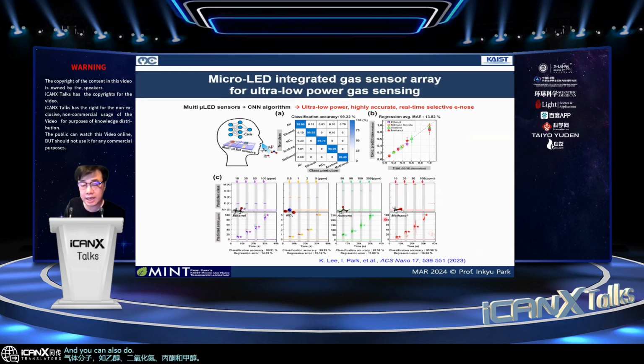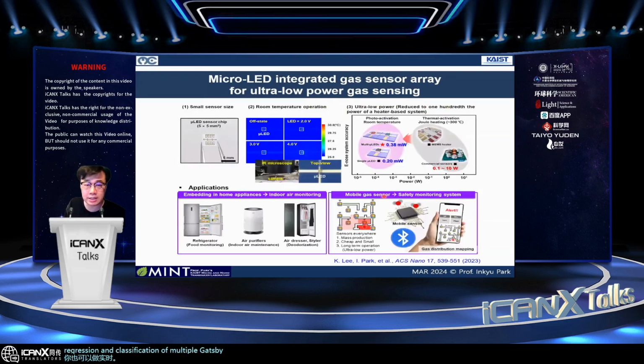And you can also do the real-time regression and classification of multiple gas species. And the biggest advantage of this one is, as I said, the power consumption. As compared to the microheater platform, usually the commercial gas sensor using a microheater platform is like 20 milliwatt, even higher. But our sensor actually has 100 times lower power consumption than the state-of-the-art MEMS-based microheater structure for the gas sensor. And also, the temperature during the operation is almost close to room temperature.